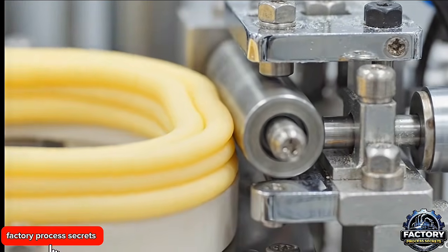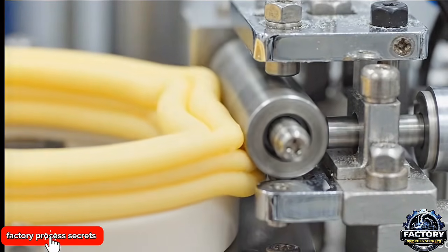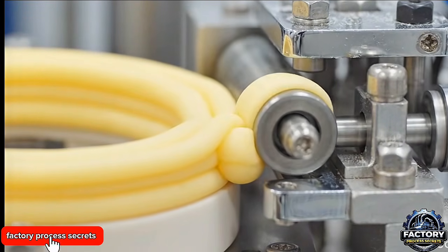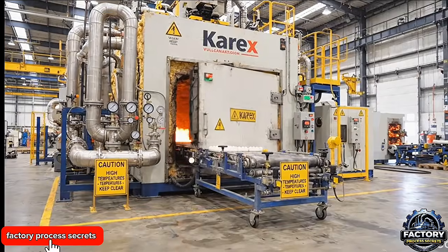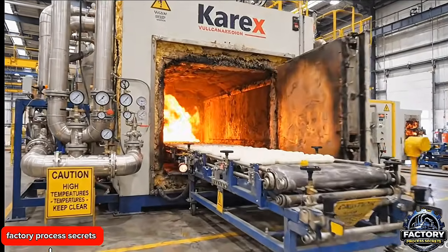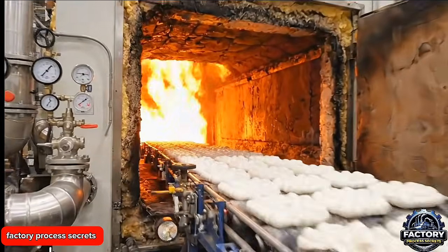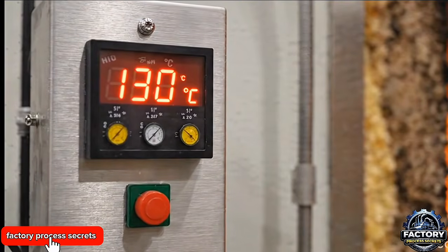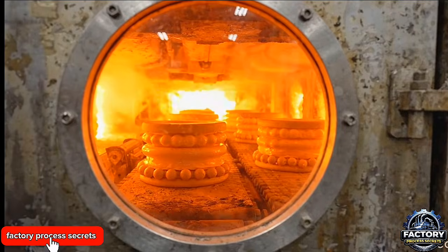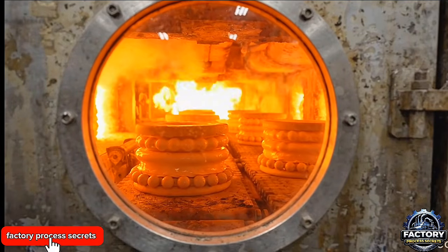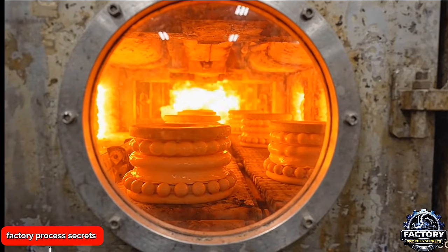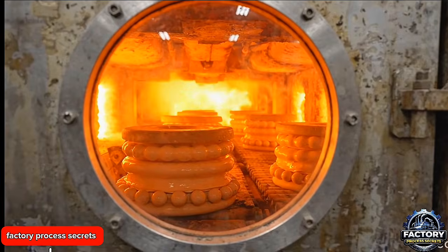Step 10. Beading. A mechanical roller forms the characteristic rim bead at the open end of each product. Step 11. Vulcanization. High temperature drives the sulfur crosslinks to form permanently between the latex polymer chains. Inside the vulcanization chamber, the chemistry locks permanently. There is no reversing this step, and what comes out of this oven is the finished latex material.